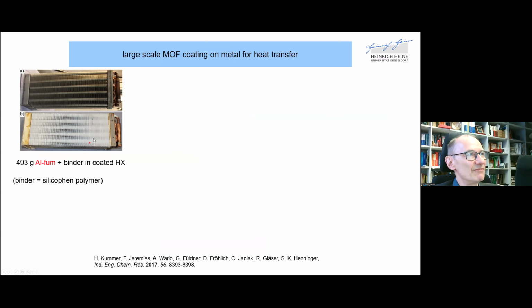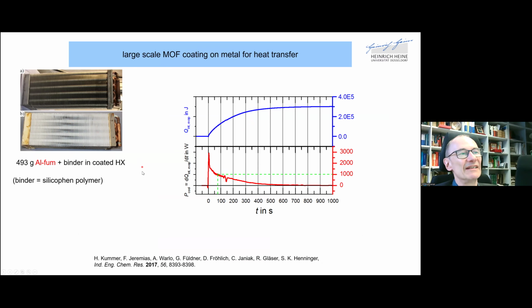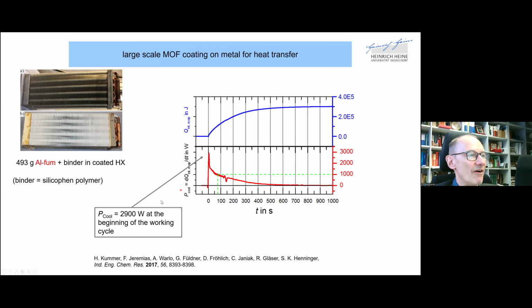So that then gave you this image, which you saw before, where now the heat exchanger is filled with a white material. And that was, in this case here, about 500 grams of aluminum fumarate and some additional binder with a weight percentage of 10% coated in this heat exchanger. So now measuring again its cooling capacity, it reaches a capacity here of 2,900 watts at the very beginning.